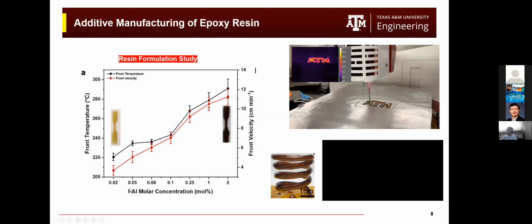So as we tune the concentration of the initiators, we were able to significantly decrease the frontal temperature, at the sacrifice of frontal velocity, but it is still 4 centimeters per minute, which is compatible with the 3D printing process. And we can see here that the color of the parts produced by different initiator concentrations is very vividly contrasted. Using a lower concentration will appear as a dark yellow, making it have very good mechanical properties.